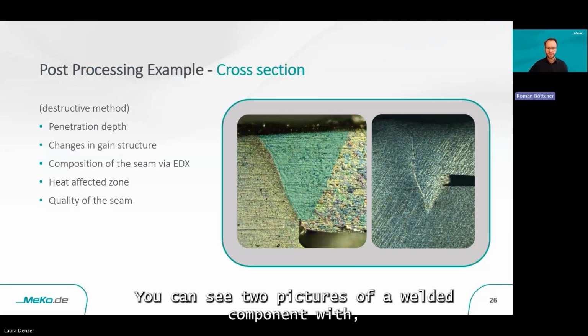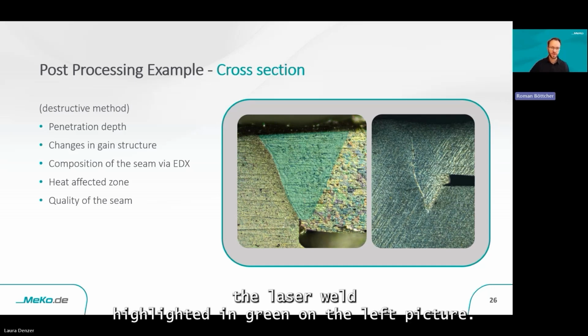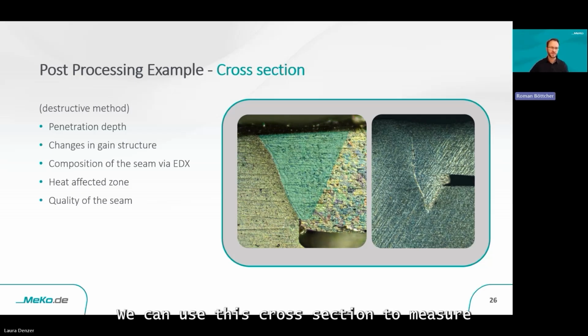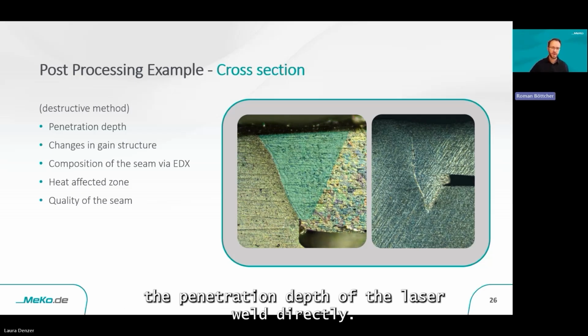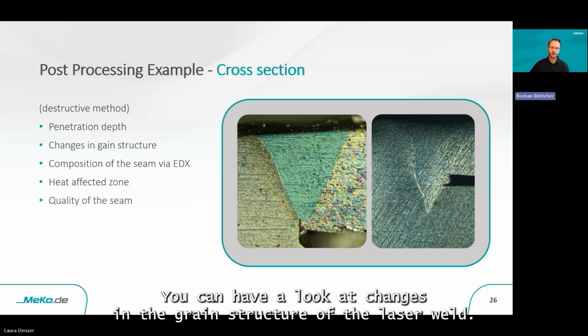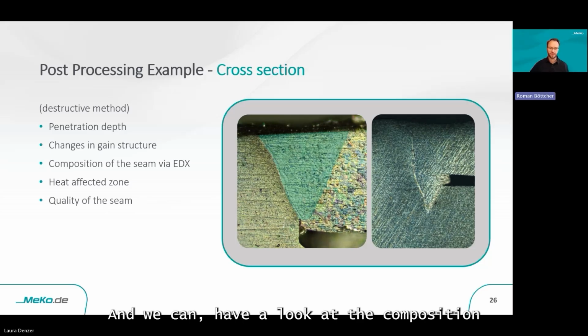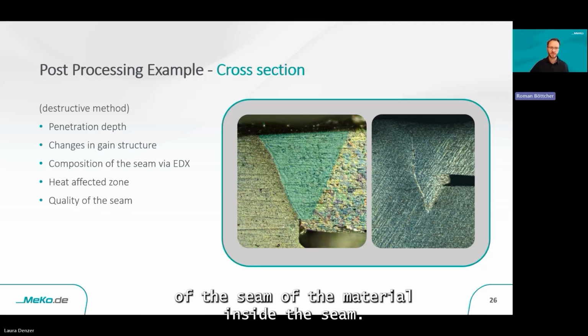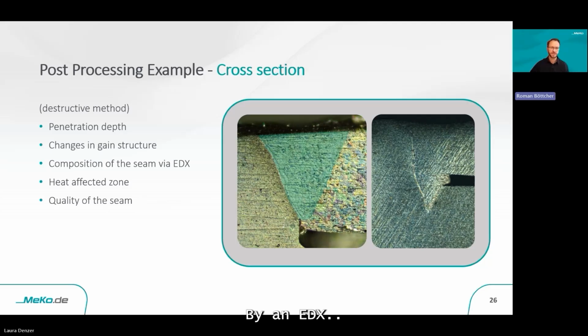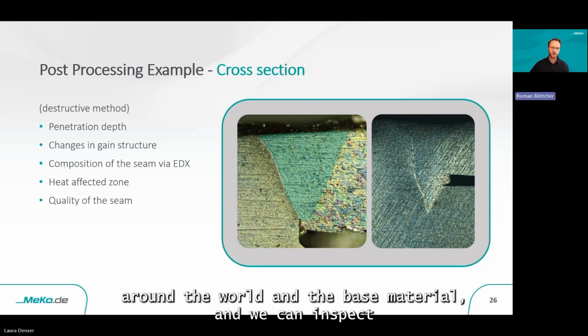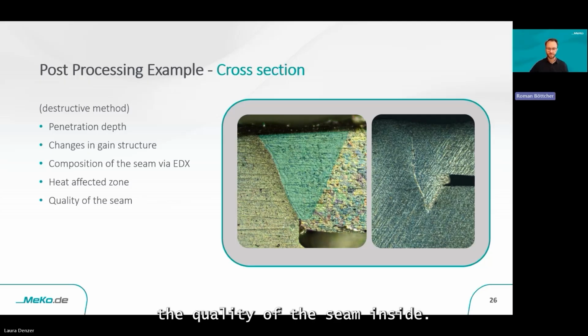There we are. You can see two pictures of a welded component with the laser weld highlighted in green on the left picture. We can use this cross-section to measure the penetration depth of the laser weld directly. We can have a look at changes in the grain structure of the laser weld, and we can have a look at the composition of the seam, of the material inside the seam via EDX, and take SEM pictures. We can inspect the heat affected zone around the weld in the base material, and we can inspect the quality of the seam inside.